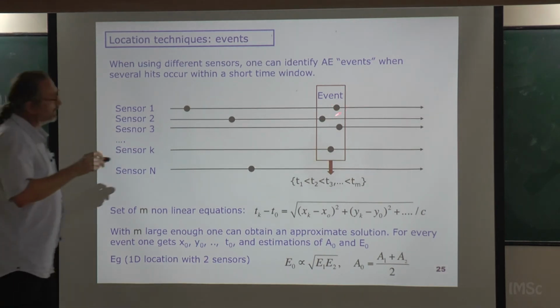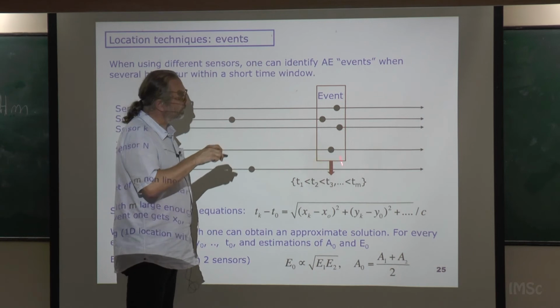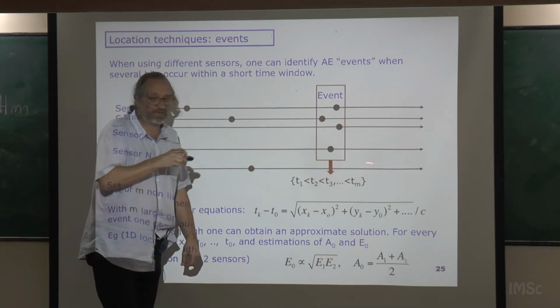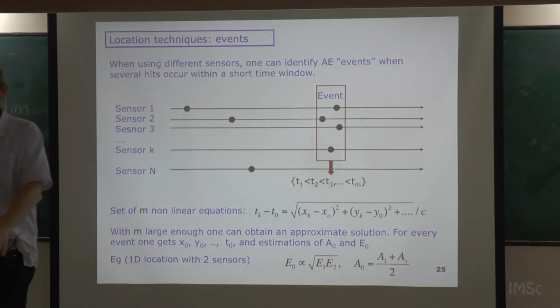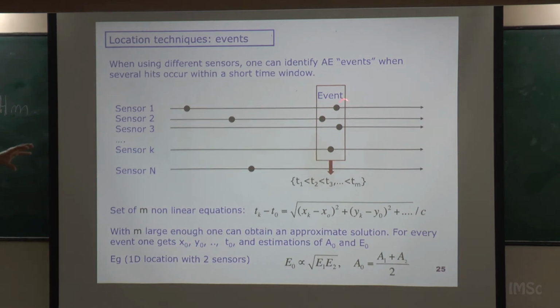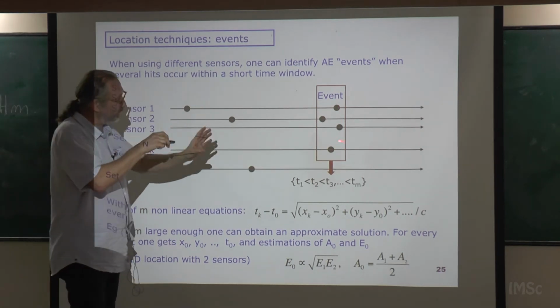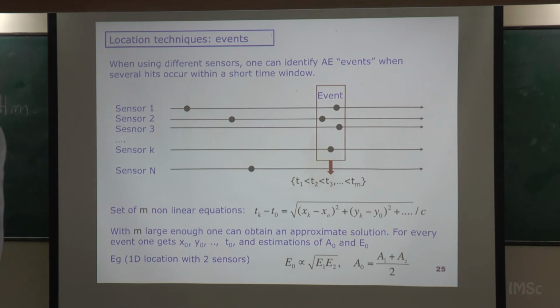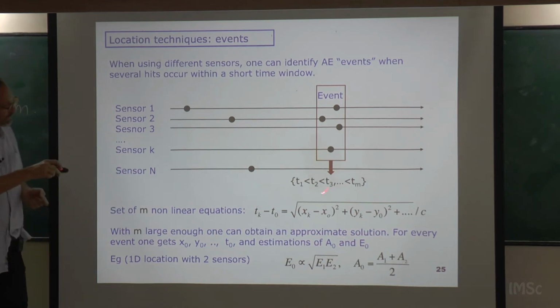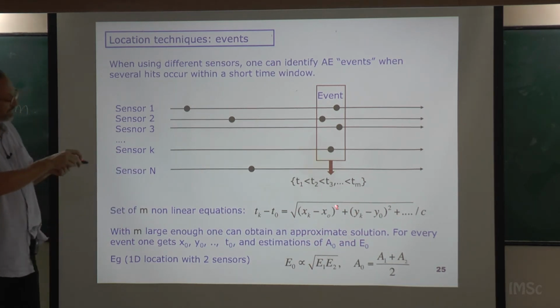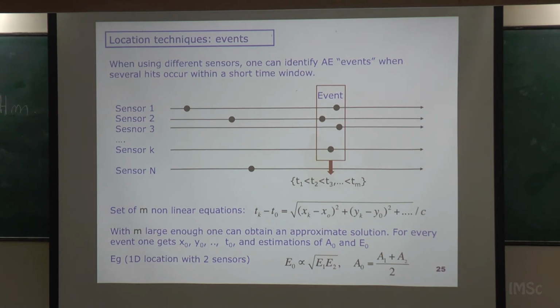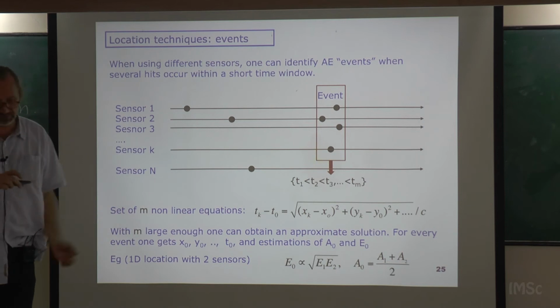And then if you do location, in fact, you have different sensors. When you detect hits in 4 different sensors, for instance, in this case, that was a 2D location, we could locate from these 4 hits, all associated to the same physical event at the source, with a certain algorithm and numerical processing. We can know where that was occurring. So we can see at what position it was occurring. We can correct what was the energy at the source, what was the amplitude at the source. Okay?